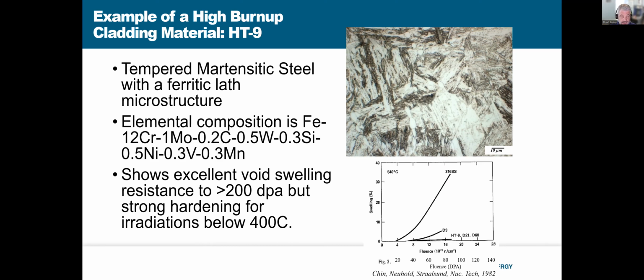And those laths provide sites for recombination of interstitials and vacancies that are made under radiation that help to be able to push this material to higher doses. It also has fine carbides in the microstructure and other things that give it good void swelling resistance.